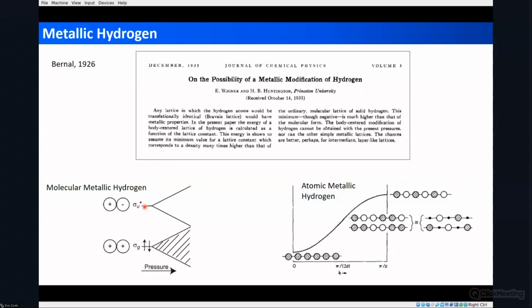So if you put hydrogen into a solid, it forms bands. And if you squeeze the hydrogen together, then you get greater overlap. And because of the overlap increasing, the bands are going to broaden. And at some pressure, you should get an overlap of the conduction and the valence bands, and this would result in what would be known as a molecular metallic hydrogen phase, and this is what could happen under pressure.